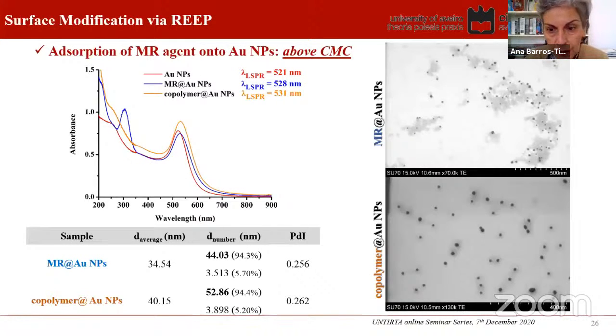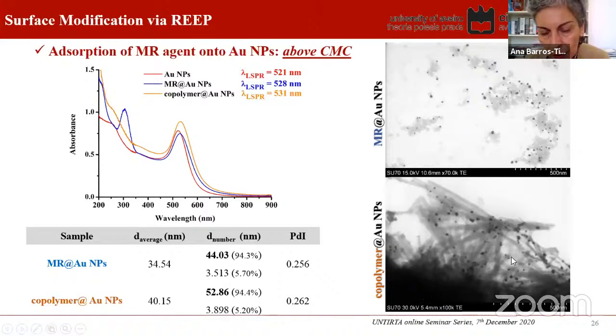And we could see that, okay, it sounded fine, that the particles, especially after encapsulation, had increased their size, but the polydispersity for encapsulated particles looked okay. The problem was that above CMC, we do not obtain only this, which sounds very good, but we also obtain other morphologies, namely fibers could be detected that were not necessarily encapsulating the nanoparticles.